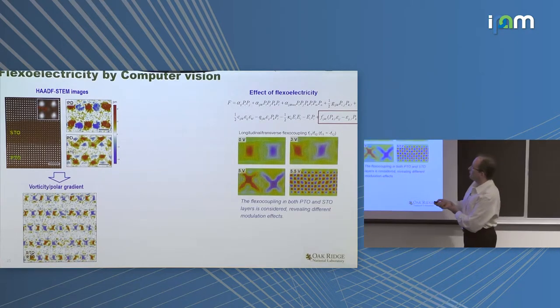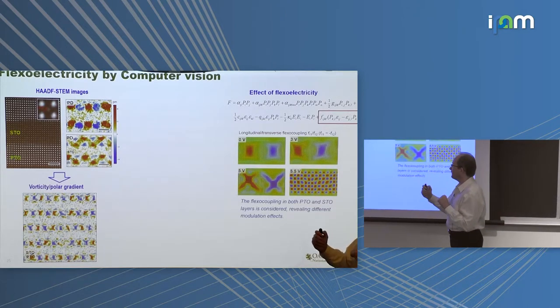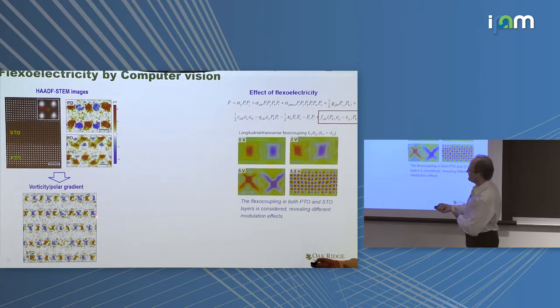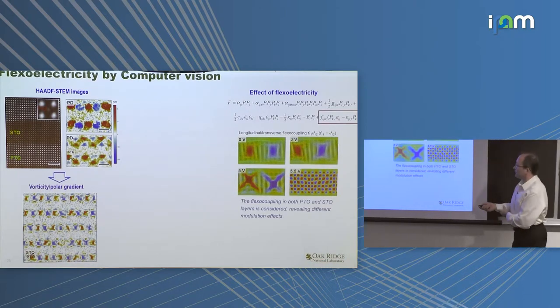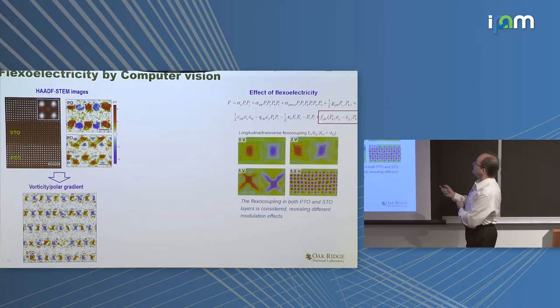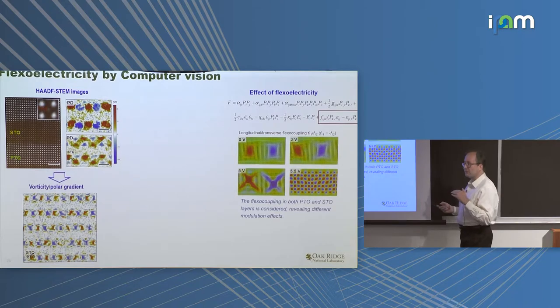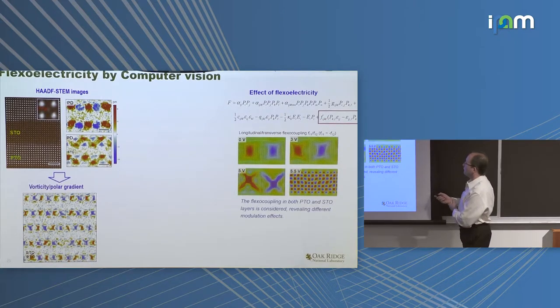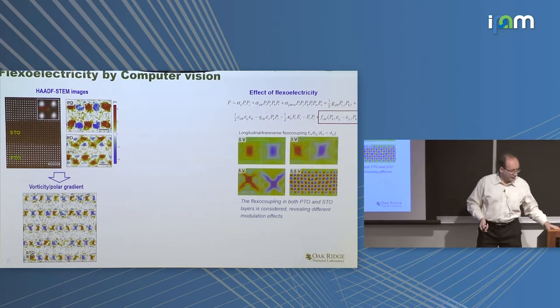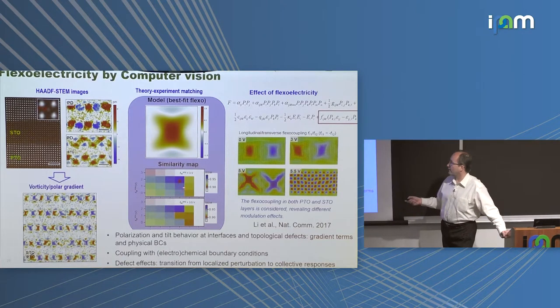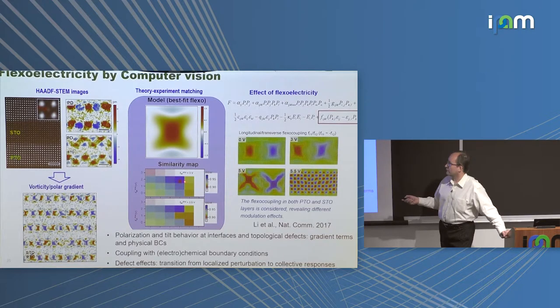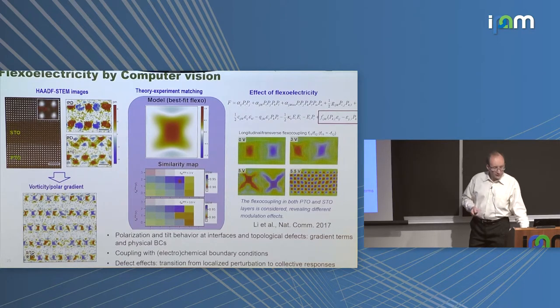I can take a Ginzburg-Landau theory with unknown boundary conditions. I can solve this for simple geometry. And then I can fit the analytical solution to the experimental observation. I observe the material on the atomic level. I have the solution on the mesoscale. I can fit the mesoscale solution to atomic observation and I get these unknown parameters. So all of a sudden, these simple equations with some unknown constants - they're still simple but the constants are now known with a pretty reasonable error bar.